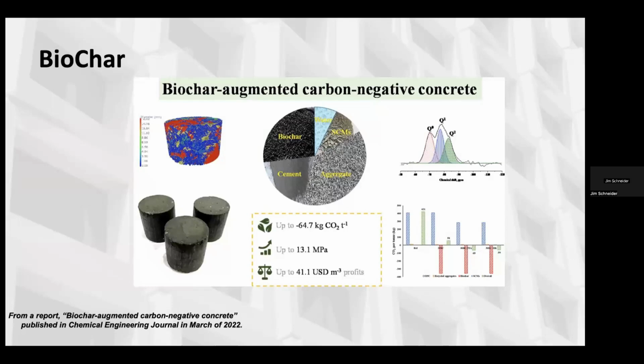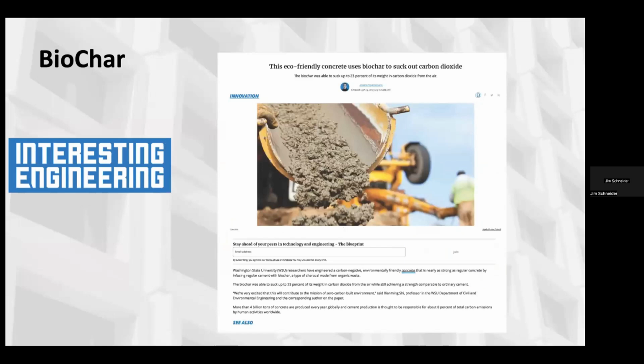Biochar as aggregate in concrete promoted the cement hydration process, facilitating the formation of calcium silicate hydrate gel and enhancing the polymerization degree via internal curing. So basically, this study was done that shows a significant carbon decrease by using biochar.